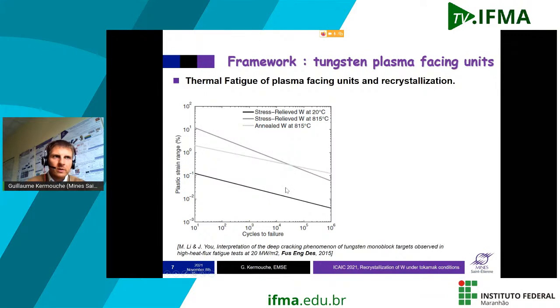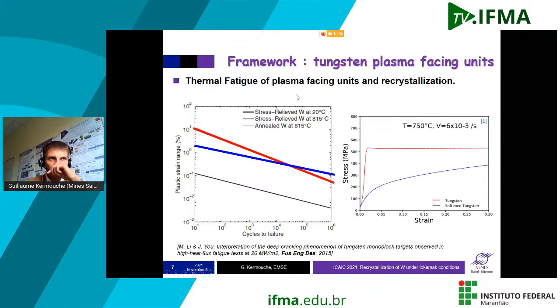Now, if we consider the material, here we have the fatigue curve at high temperature, so 800 degrees C, and you have the fatigue curve for the raw material. So before recrystallization, the red part, you can see here the stress strain curve, and here the one for the recrystallized material. So what we call the softened tungsten. It has been recrystallized, so it's softer. What you can see is finally there's a shift from this curve to this curve. So the recrystallized material finally is, I would say, worse than the non-recrystallized material from this curve.